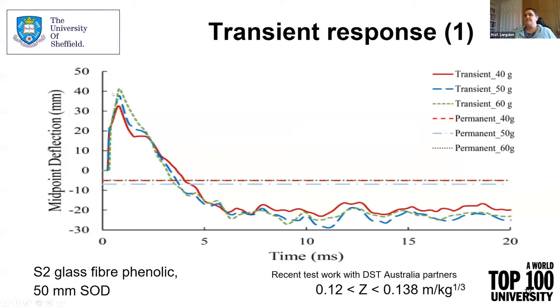And then you can see after they peak, they rebound and they go down to negative displacements, which means they've deformed in the direction towards the blast, so in the opposite direction to which you would imagine a structure would move when it's subjected to a blast load. The dotted lines that are non-variant with time that are plotted across the middle, at about -5 or -6 millimeters, those are the permanent deflections of the panel measured afterwards, after the testing is totally completed.